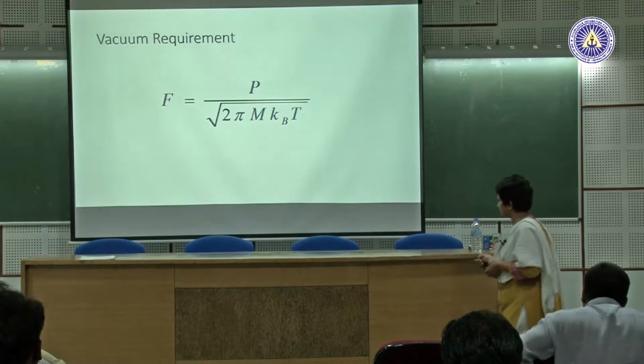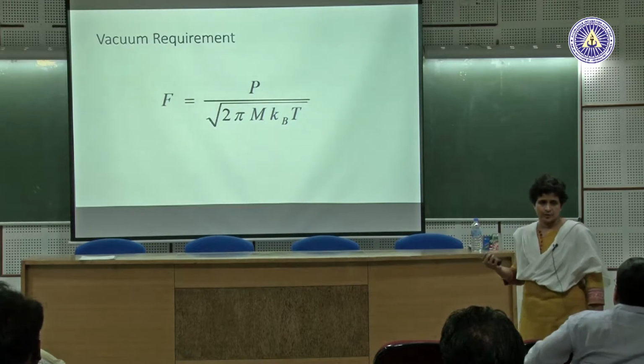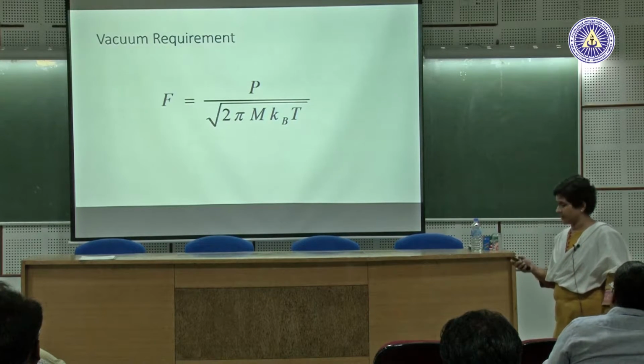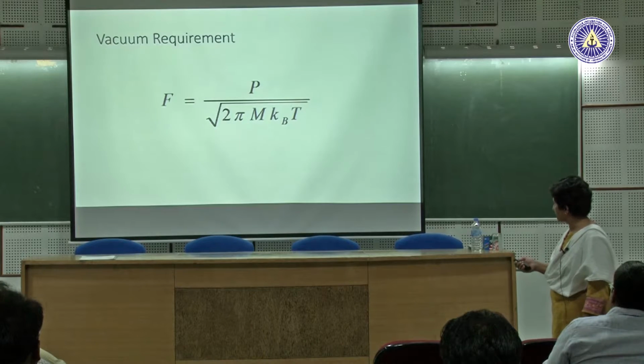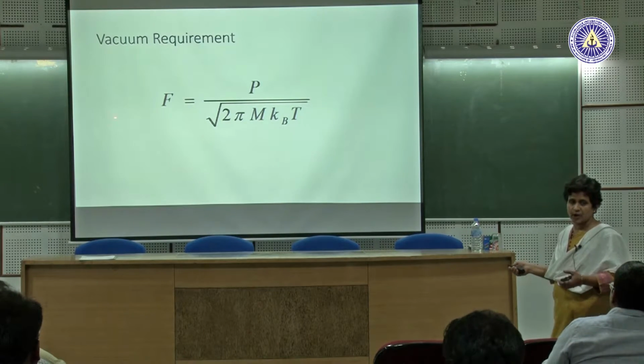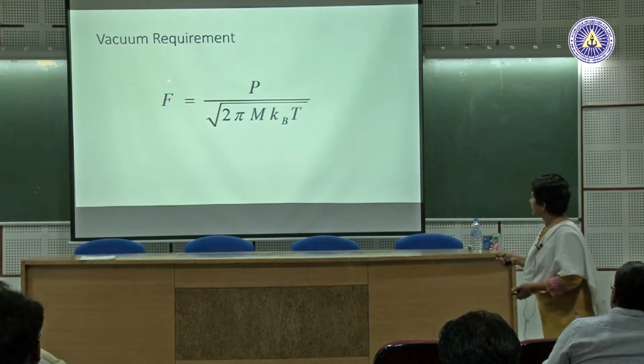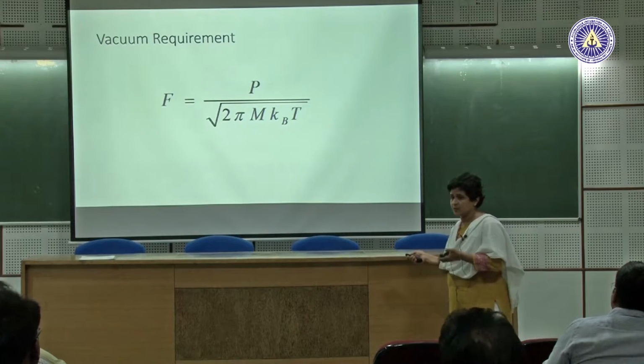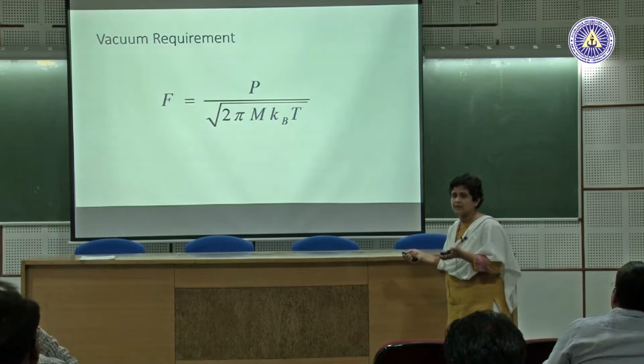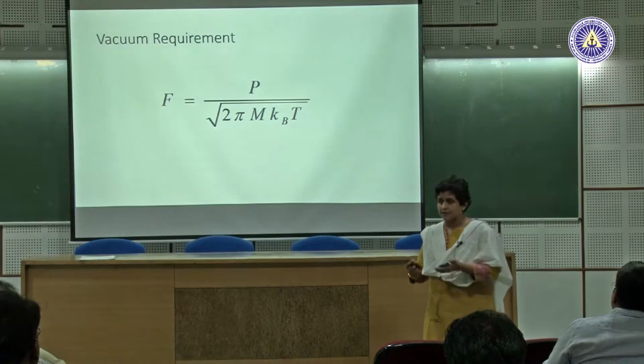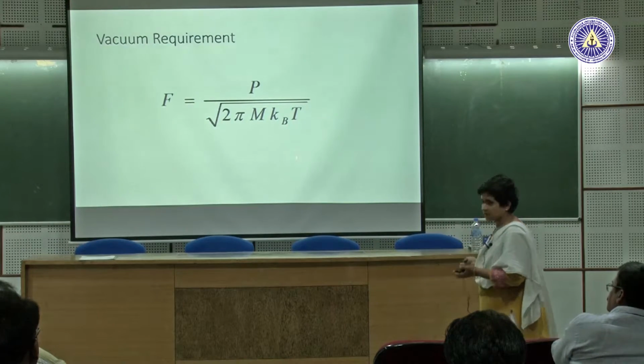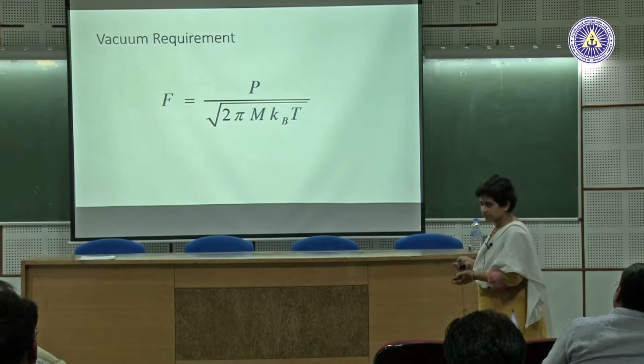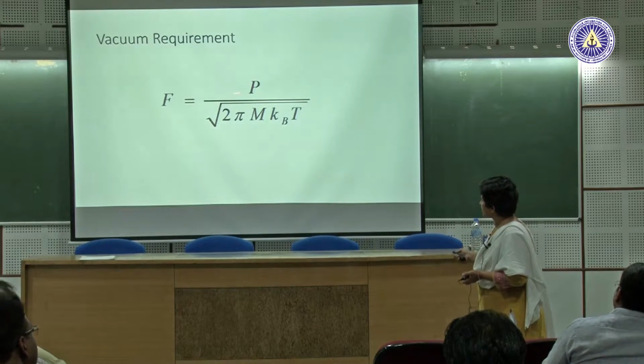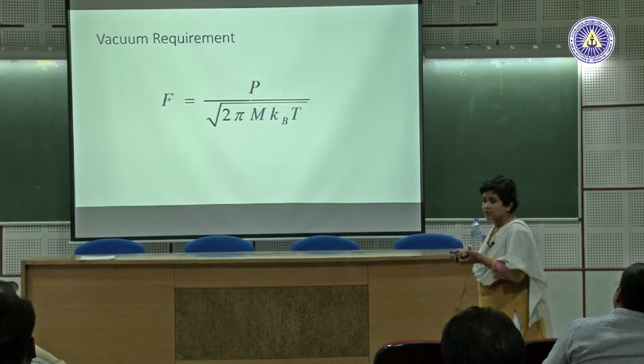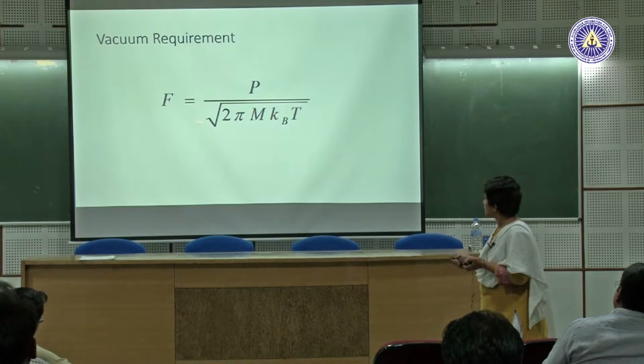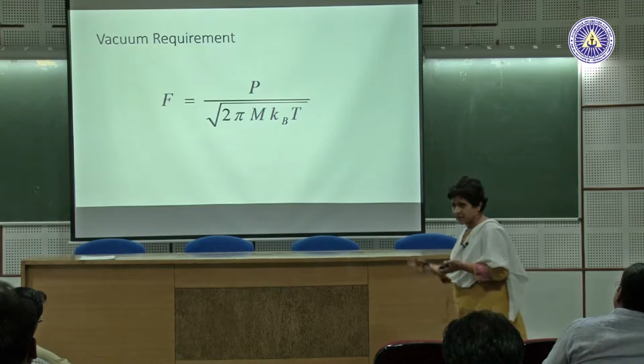Now there is a lot of science that goes into it. You can actually calculate the deposition rate. If you heat up a material, this is the flux of vapor phase atoms, let us say in the case of thermal evaporation of metals, the number of atoms per centimeter square per second coming to your substrate. That is decided by the thermodynamic property of the material you are evaporating, the pressure in the chamber, and the temperature of the source material, and the mass of what you are evaporating. This is the partial pressure of the material that you want to evaporate, okay? So if you have a material which has high partial pressure, it's easy to evaporate.